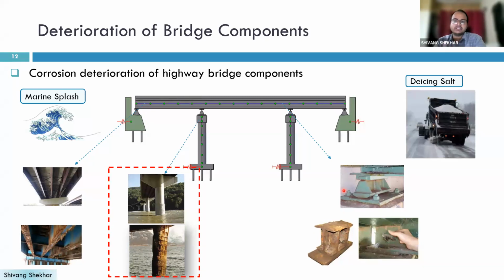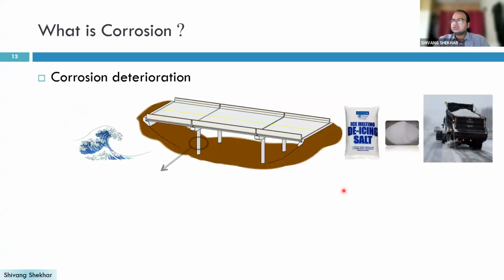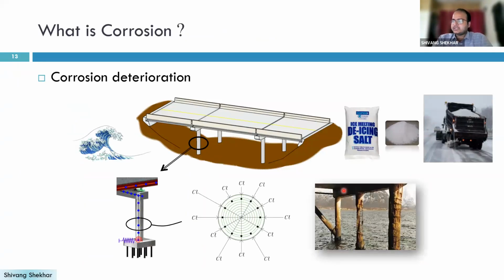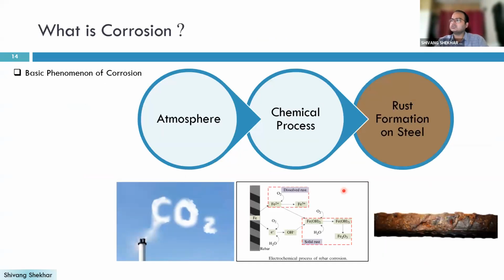So we'll first look into the reinforced concrete bridge piers, or bridge columns, because the lateral load carrying capacity of a bridge depends on the bridge column. I have just taken a bridge column to show you that, due to the ingress of chloride ions, if there is chloride-induced corrosion due to a high amount of chloride content, there is a corrosion of reinforcement. I'm not going to explain the process of corrosion. We all as students have learned that some chemical process occurs that leads to the formation of rust. This rust occupies a larger volume than the steel. That leads to expansion, then cracking and spalling of the concrete.